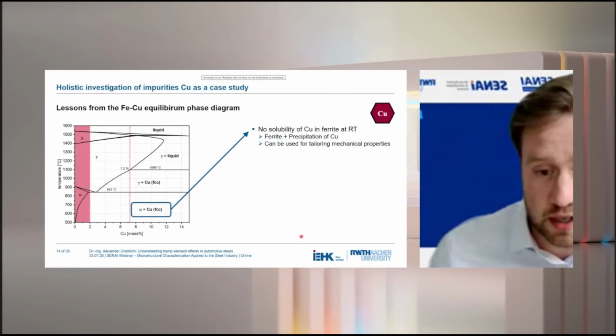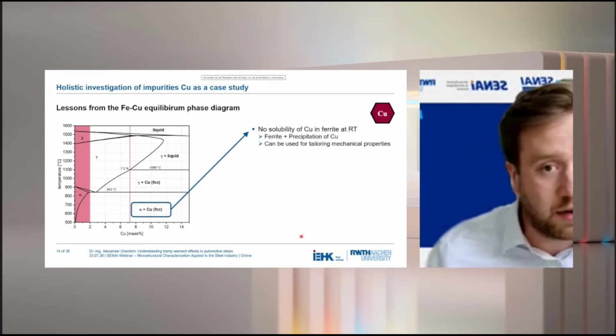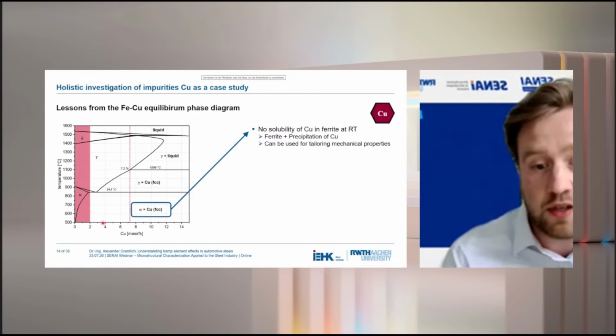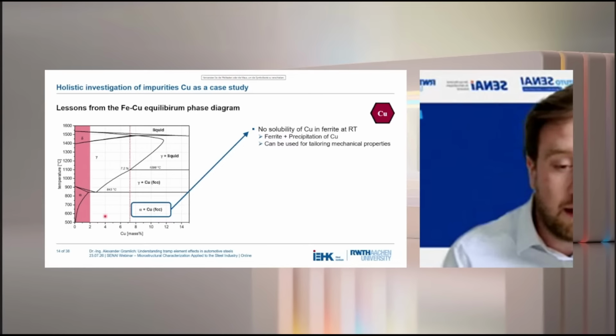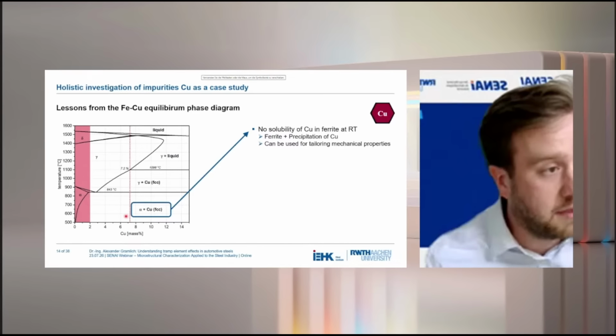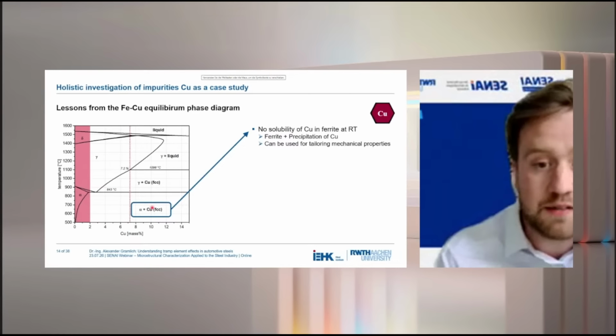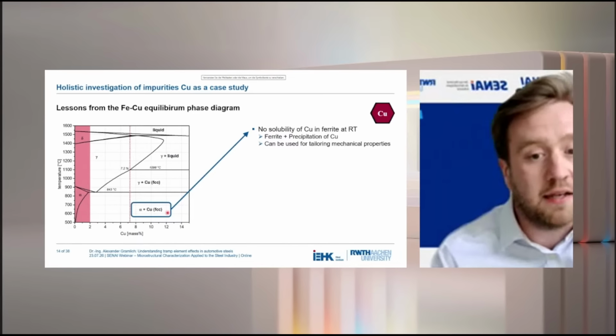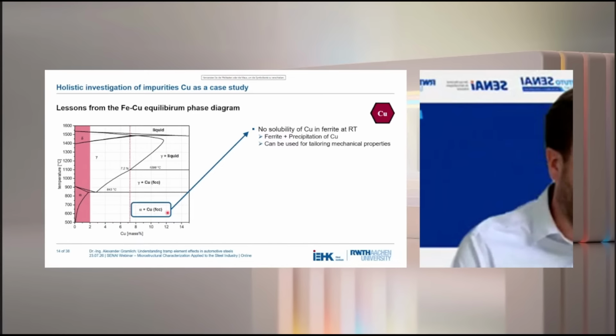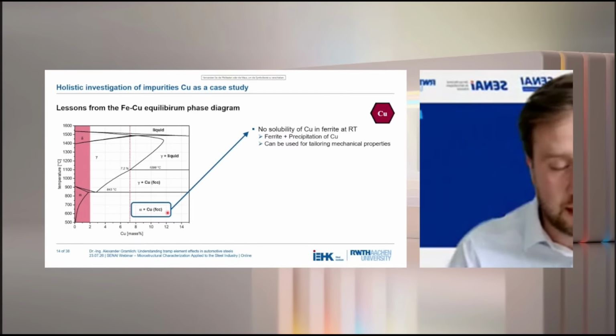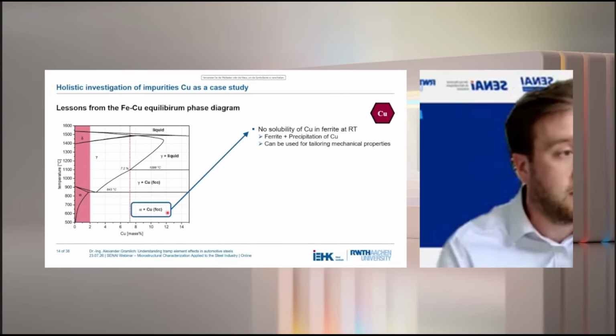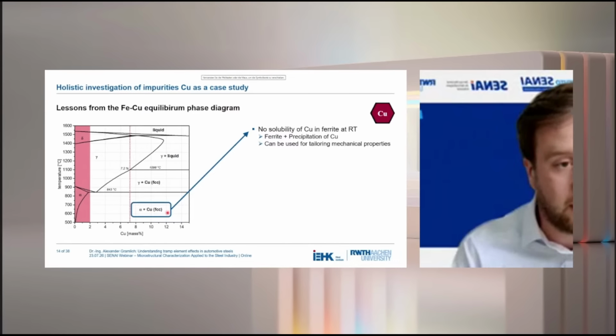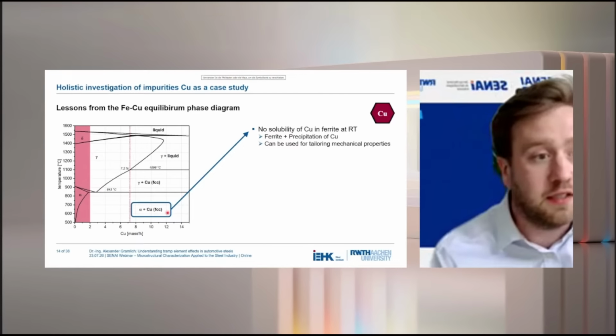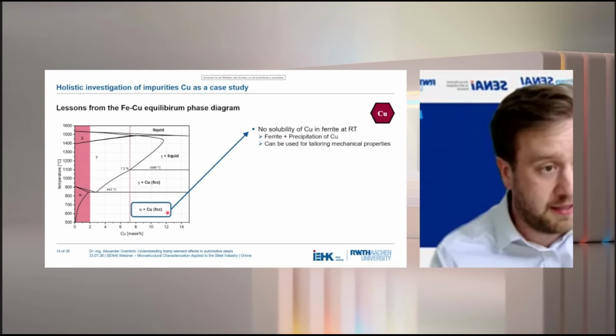As a material engineer, I always go first to the phase diagram. And when I'm looking at the iron-copper diagram, I can see that at low temperatures, we basically have a very limited solubility of copper, and Thermo-Calc gives us here basically that we have ferrite and a copper FCC phase. From this, we can already more or less expect that we can use copper as a precipitation strengthening element, and we can use it for tailoring the mechanical properties.